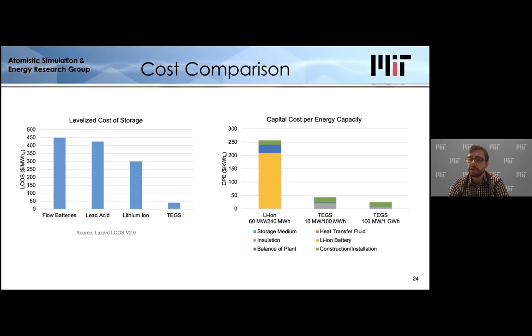Something interesting to note here is that the costs for the larger system are about half the smaller system. And that primarily has to do with the fact that as you scale up, your insulation cost goes down because your surface area to volume ratio decreases. So you can think of it in the same way that a small person gets cold faster than a large person. So basically, there's an advantage for scaling up to very large sizes.